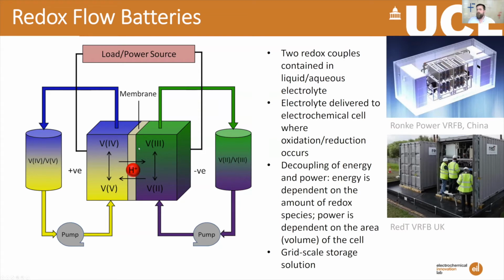But the good thing about flow batteries compared to lithium-ion batteries, for example, is that capacity can be tweaked just simply by adding a larger tank. So you've got more electrolyte, you've got more energy capacity. For higher power, you can just design a bigger cell in the middle so that you can convert more of it, charge more of it per second. And so this is really good. It gives a lot of design flexibility. There's a lot of flexibility in chemistry as well.